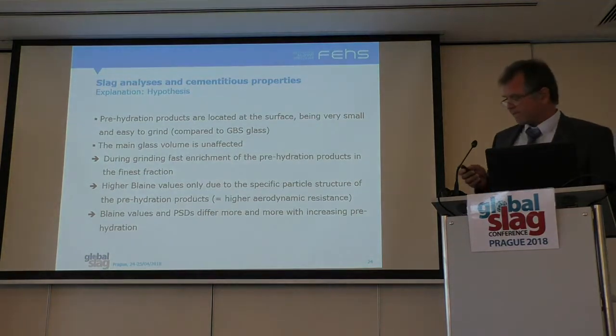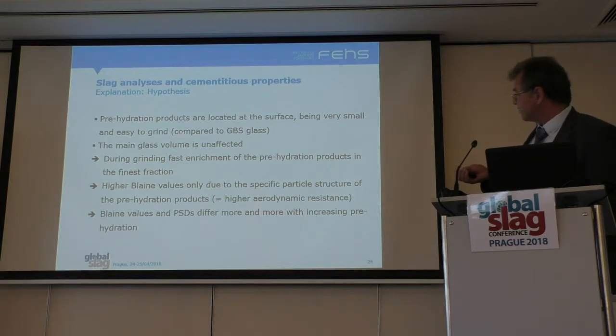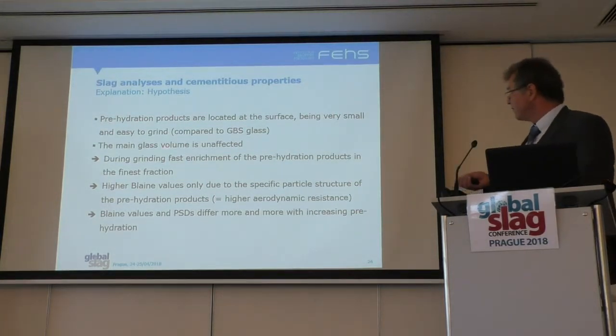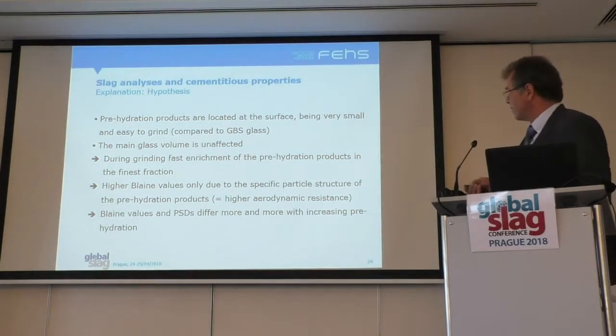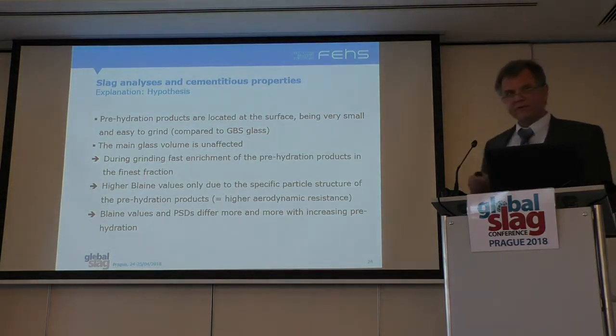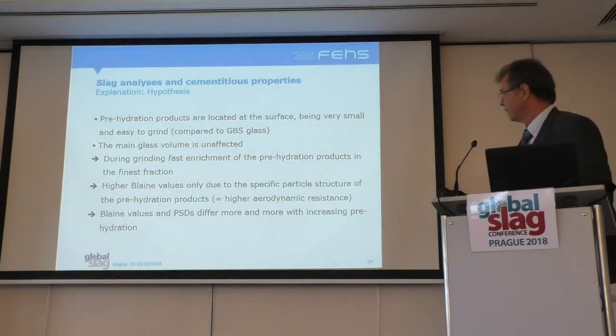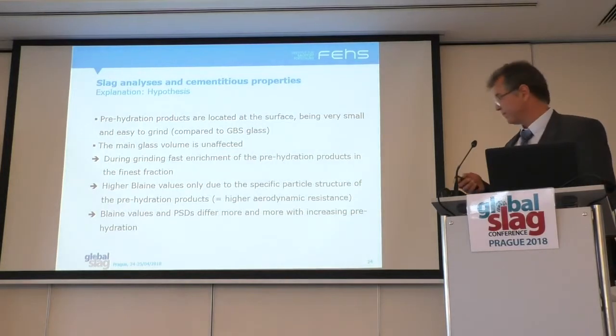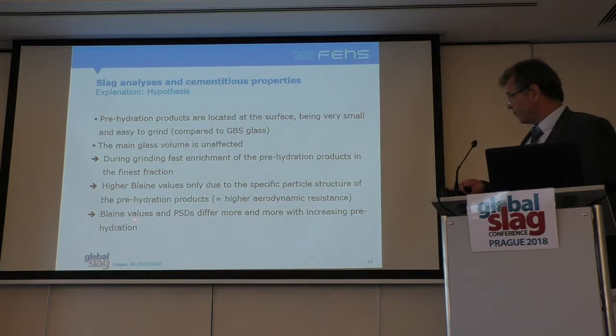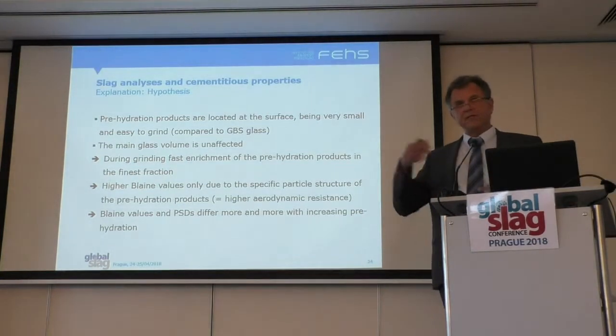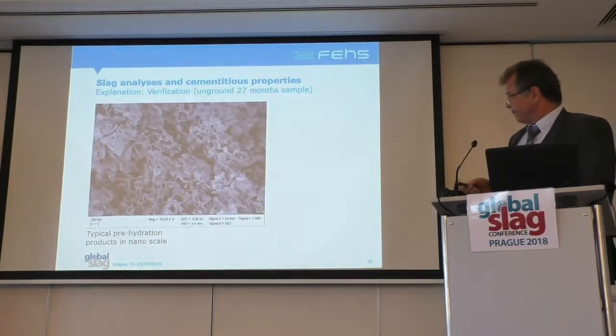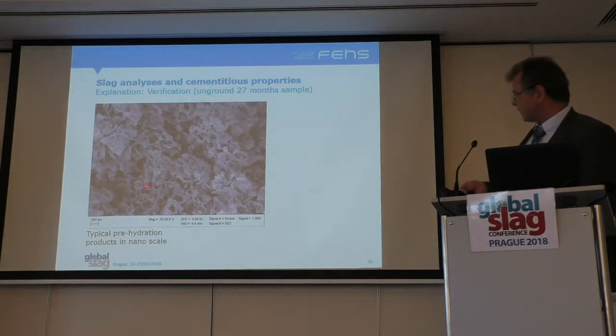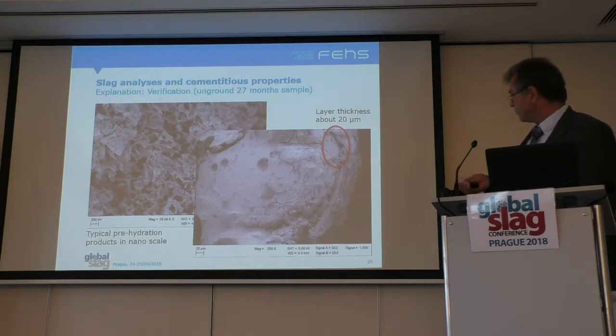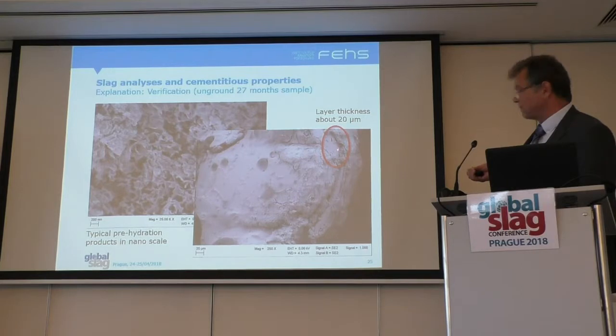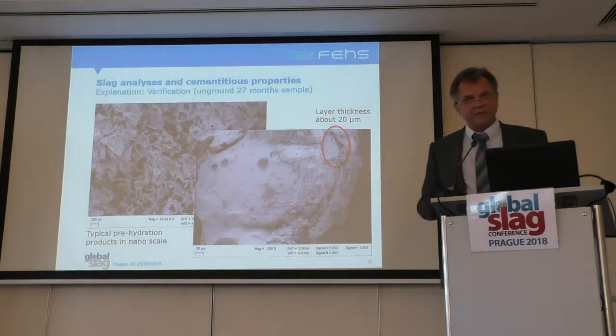The explanation, we made a hypothesis. Prehydration products are located at the surface as we saw, and the main glass volume is unaffected, that we measured. So we think during the grinding process we have a very fast enrichment of the prehydrated surface. Therefore we get very fast, very high Blaine values, and we see that between Blaine value and particle size, real fineness, there is an increasing difference. That's typical for prehydration products in nanoscale at the surface. And if you look at the thickness of this layer, it's only about 10 to 20 microns. And the main volume of the GBS grain, as you can see here, is unaffected by any storing conditions.